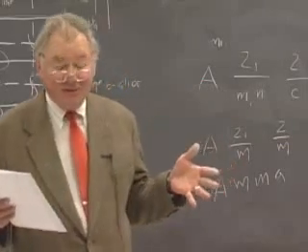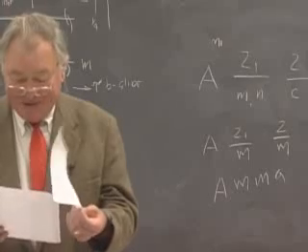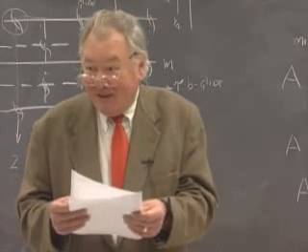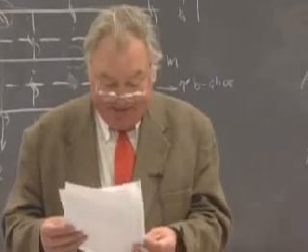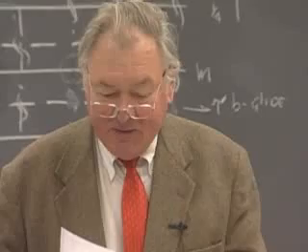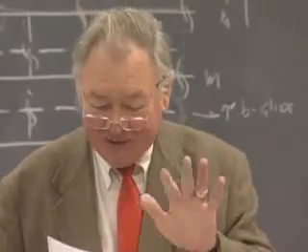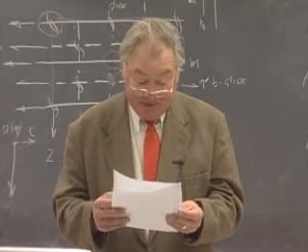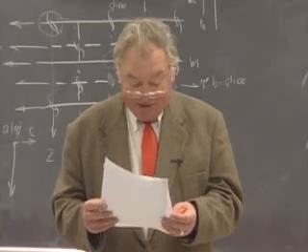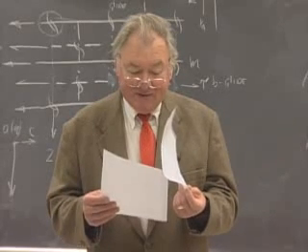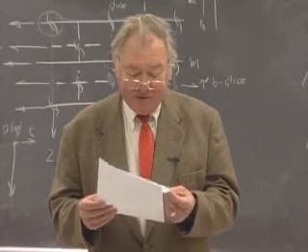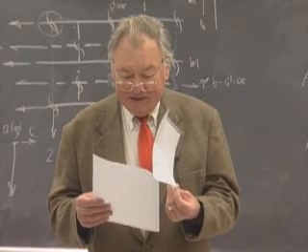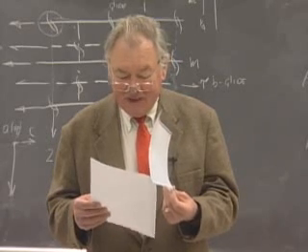Notice, however, the exquisite number of general and special positions that are present in the space group. The general position has the letter U. You've gone through almost the entire alphabet before you've labeled all of these positions. And they're, again, either on the mirror planes, but now there's a vertical mirror plane, a diagonal vertical mirror plane, horizontal mirror planes halfway along each of the axes, mirror planes halfway along the diagonal translation. So there are lots of positions of point group M, lots of positions with point group 2mm, and then finally 2 over m, 2 over m, 2 over m, and the highest symmetry 4 over m, 2 over m, 2 over m, which occurs at the origin, at the center of the cell, and at the positions 0, 0, 1 half, and 1 half, 1 half, 1 half.